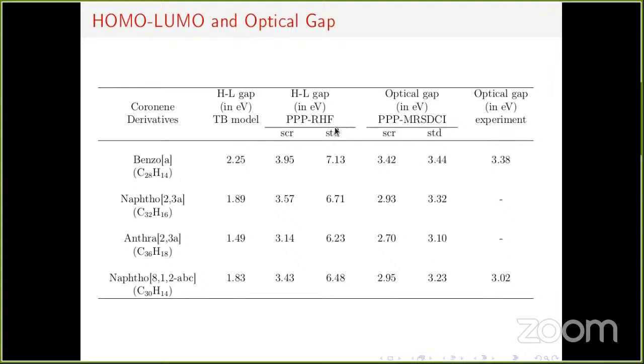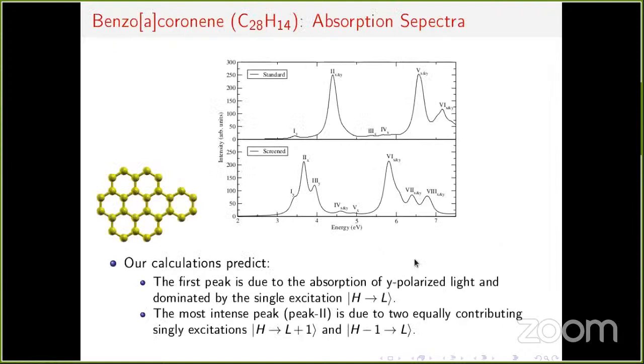Then we performed PPP model calculations at Hartree-Fock level and at MRSDCI level, that is including the electron correlation effects. So you can see that the best agreement with the experiments is obtained with MRSDCI calculations, electron correlated calculations performed using the screened parameters, as we expected. But let us go somewhat deeper into the individual molecules.